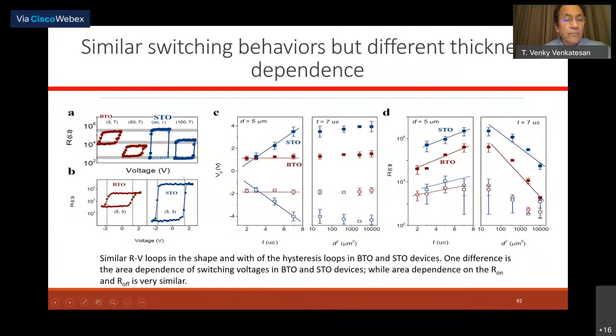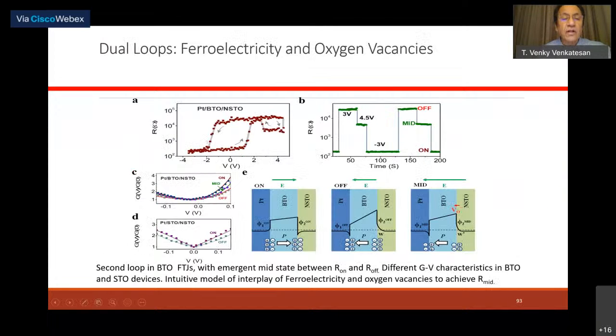And in fact, if I can combine them in BTO, I can produce this type of characteristic, where this on-off ratio is coming from the ferroelectric tunnel junction, and this on-off ratio is coming from the oxygen vacancy induced filament formation, and that gives you this kind of state. So you can create multi-state memories, as is shown here, by using the combination of both the oxygen vacancy motion and the ferroelectric tunneling.